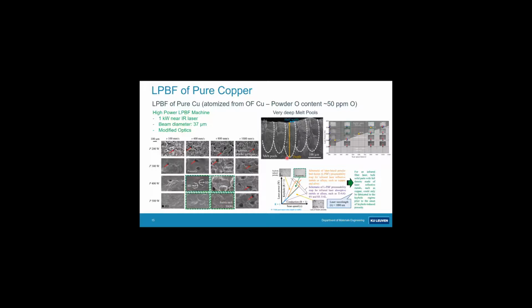But when you look in detail at your melt pools in your microstructure, they are very deep. So you typically, from the welding literature, define a ratio, which is the depth over half width. So that's the R value, and that is very high and certainly higher than 1, which is typically in the so-called keyhole mode and not anymore in the conduction mode. And when you make a plot of laser power versus scan speed and you compare all the microstructures you generate, then you see that we could only successfully process pure copper in a very narrow processing window, which was really at the transition between conduction and keyholing mode in the keyholing regime. But as mentioned here, prior to the onset of keyhole-induced porosity.